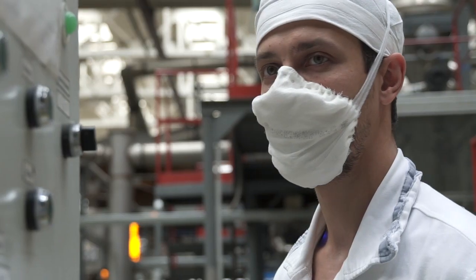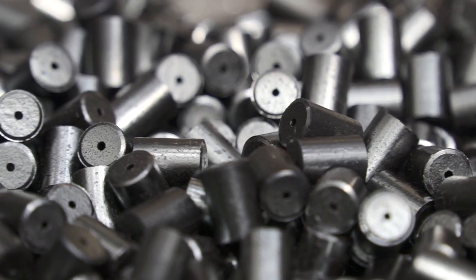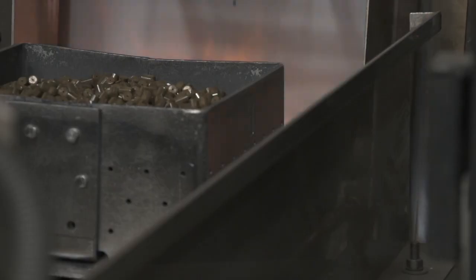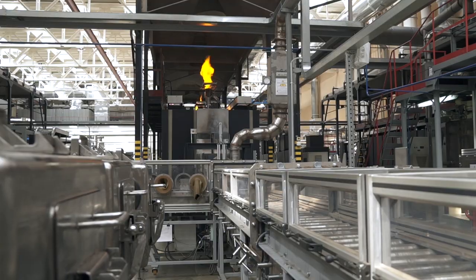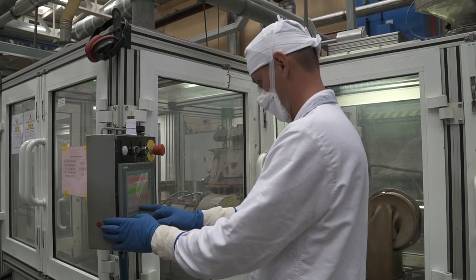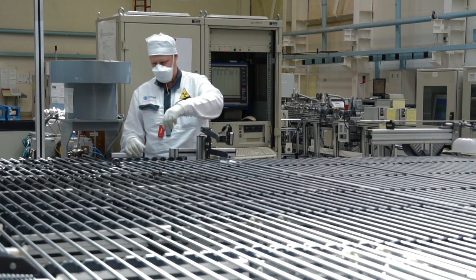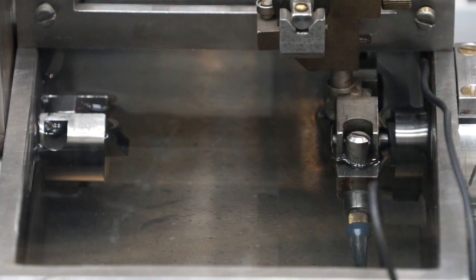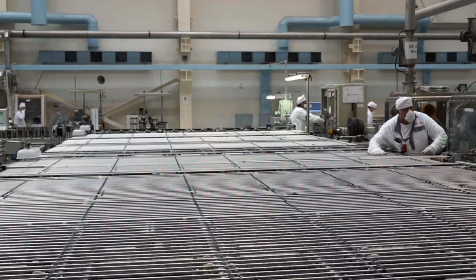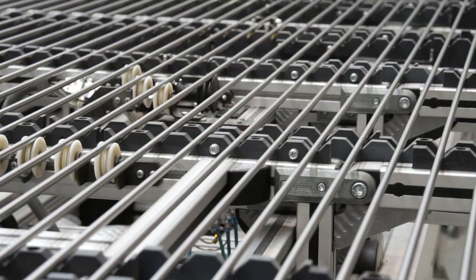This is the production line for ceramic uranium fuel. Here, uranium dioxide powder is pressed into pellets, which are then placed in a reducing hydrogen environment. Further processing and quality control are done automatically. Finished pellets are placed in zirconium claddings. Assembly, pressurization, and evaluation of the element's performance are all parts of one process.